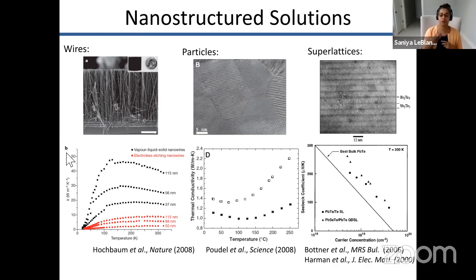So we can make the material into nanowires. We can grind it up until the features of the material are small enough that they would impact the carrier transport. Or we can even build it up layer by layer where we're controlling the structure at a very, very small scale. We've seen this already done with nanowires, bulk nanoparticle materials, and superlattice materials, where all of those materials are ones where nanostructuring has been done to improve the material figure of merit.